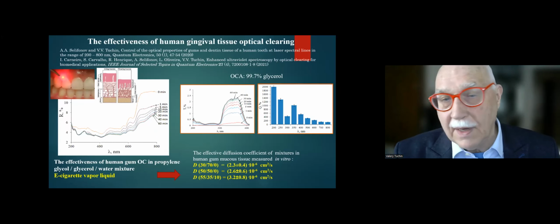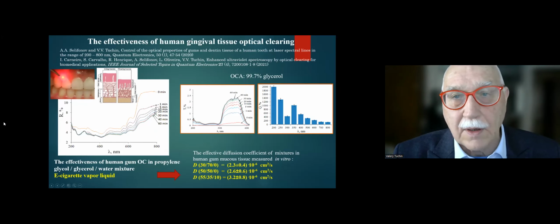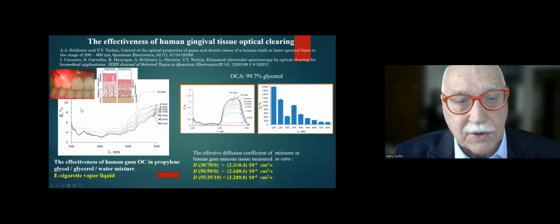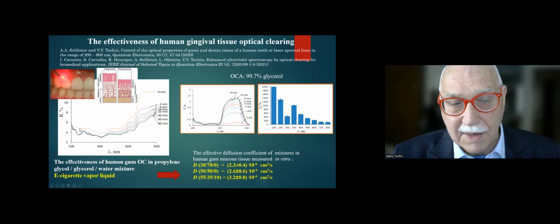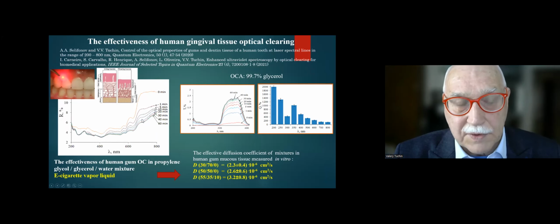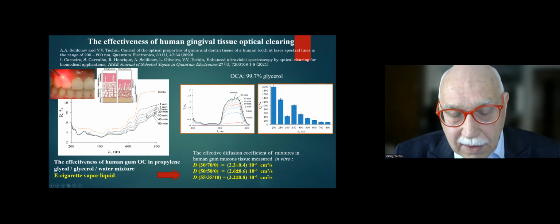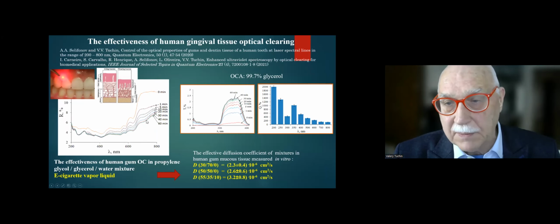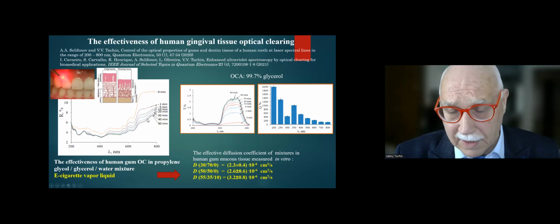So the same for oral mucosa, for gums. You see here, this is another technology. It's the back reflectance, not transmittance, back reflectance. Also, we see less scattering. Therefore, with time we have a decay of the back scattering. That means that we have some refractive index matching and so on.